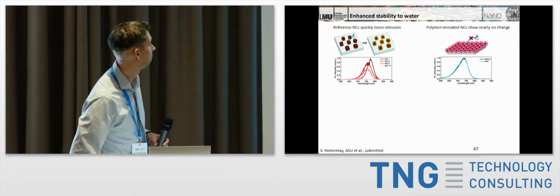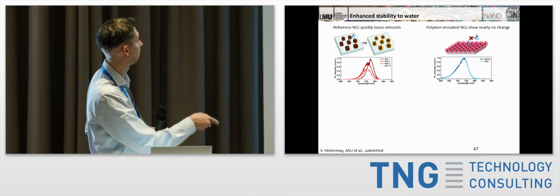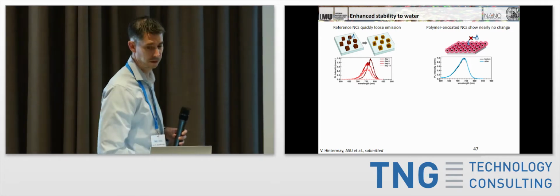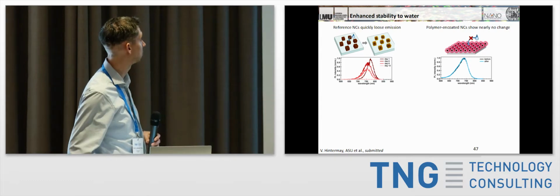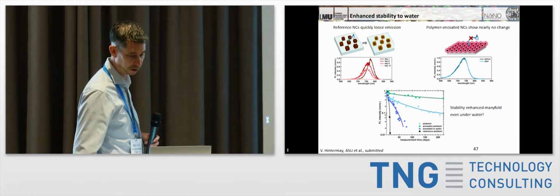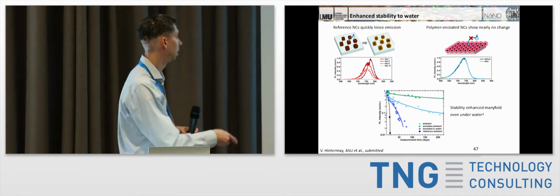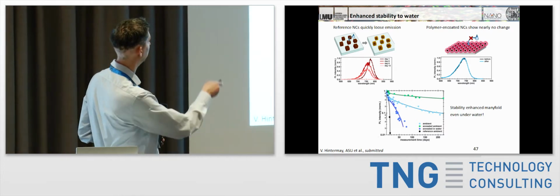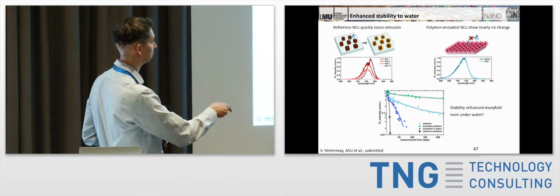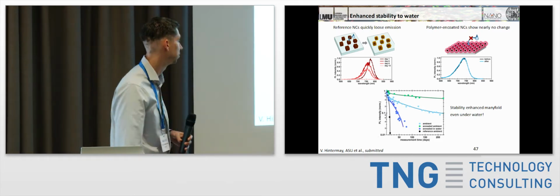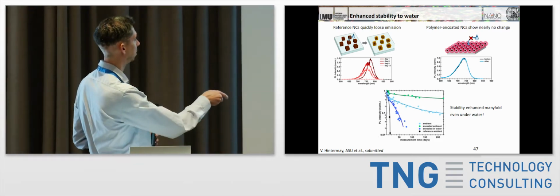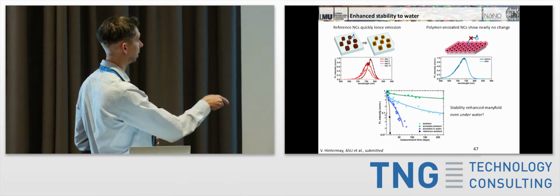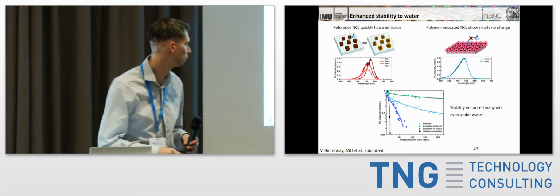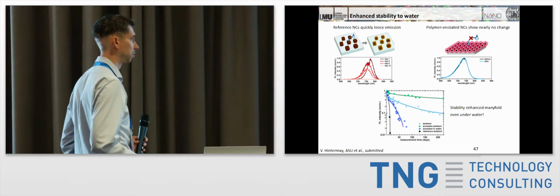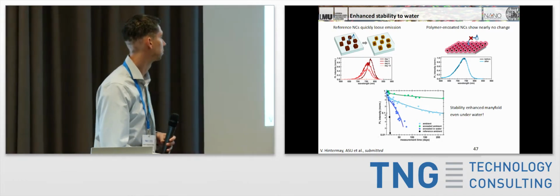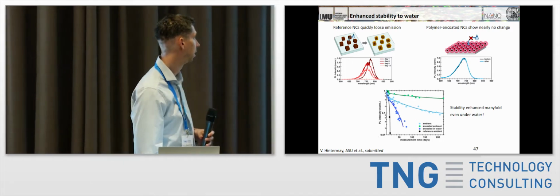In the case of our thin films, basically we can have them sitting out in a sample, and we can even put water on top of them, and they don't change the spectrum at all. And now if you monitor the total photoluminescence intensity over time, you can see this here, this black curve is essentially one of these nanocrystals, so it drops off. This is them sitting out in air. After about 13 days, you can't see anything anymore. In comparison, this green curve is what we now have in these perovskites sitting out in air. We've now reached over 400 days, and they're still efficient at about 40%, so a factor of about 40 longer.